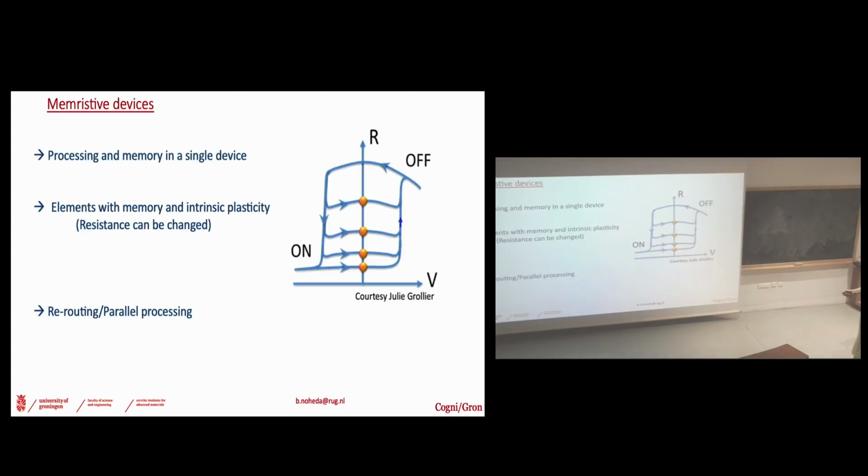Okay? So this should be quite interesting for what we discussed the other day, to use these materials for neuromorphic devices, because in principle you can have a polarization that you switch quite fast, because it's about local dipoles, unit cell level dipoles, balancing somehow with the oxygen vacancies that are moving quite slow. So you have two time constants and different dynamics of different processes, which is what we actually needed to create this hysteretic behavior, if you remember. So it seems like these materials could be very interesting for memristive applications.